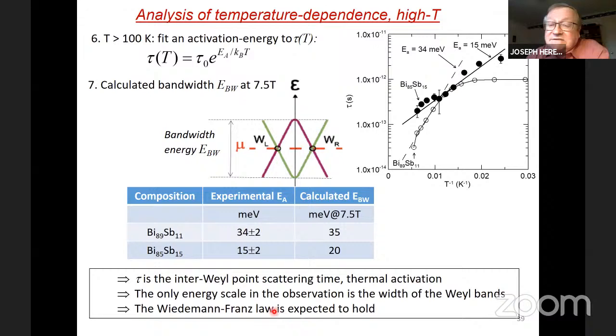Now, it is under these circumstances that the scattering time should be the same for electrical and thermal measurements. And it is under these circumstances, mu equals zero and the same scattering time, that the Wiedemann-Franz law is expected to hold. And here comes the hard part of the talk, which is the verification of the Wiedemann-Franz law. Like I said, the measurements up to here have taken a little less than a year. The last fourth of the talk has taken 18 months.